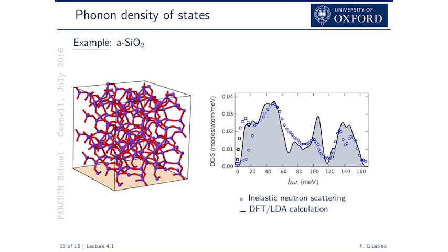The second thing is that in the neutron scattering data, there are various other complications, like the cross section for the neutron scattering, which changes the heights of the peaks. And in this calculation, I did not correct for that. Essentially, this is just a phonon density of states. I'm not taking into account the scattering cross sections. So clearly the heights of the peaks are not going to be identical. But you can see that we are quite close, which is quite impressive.